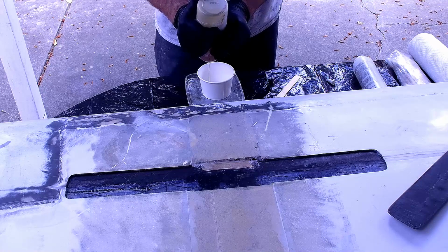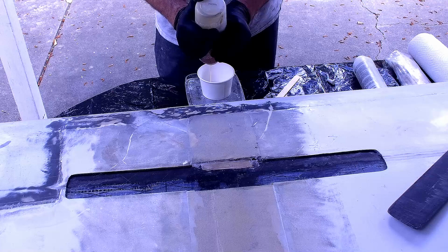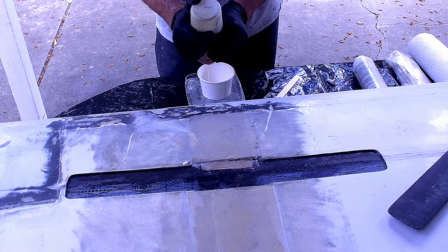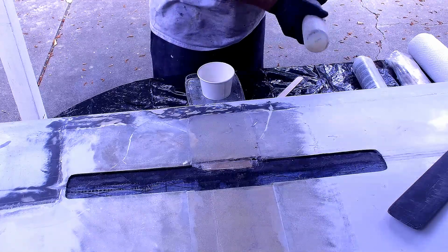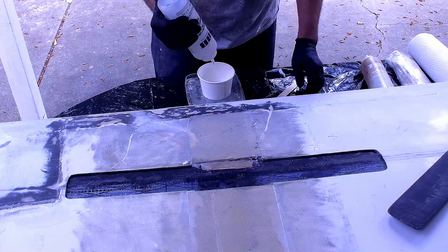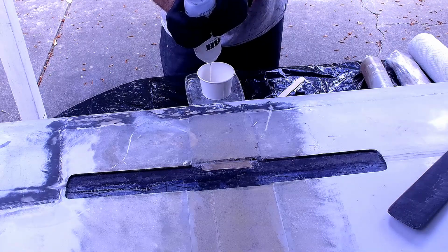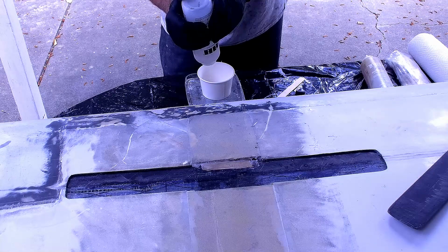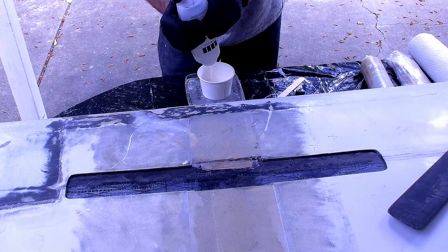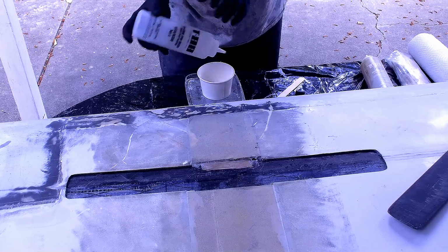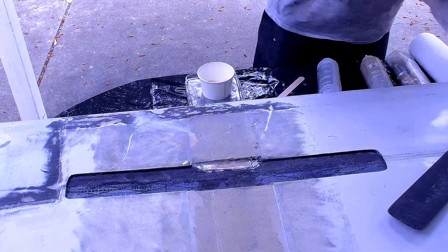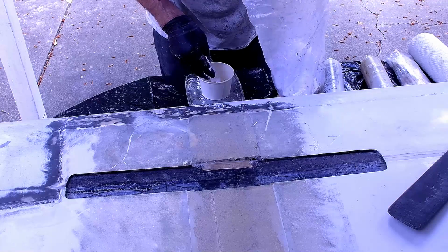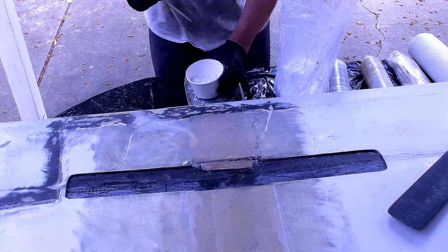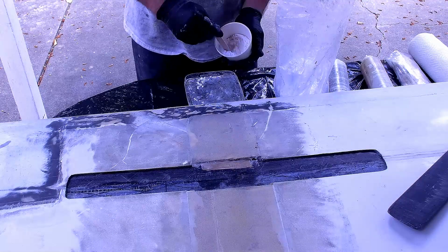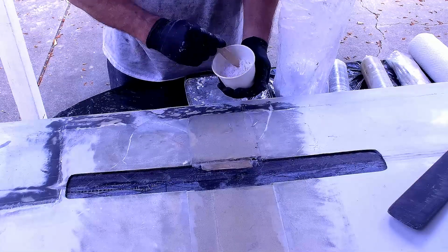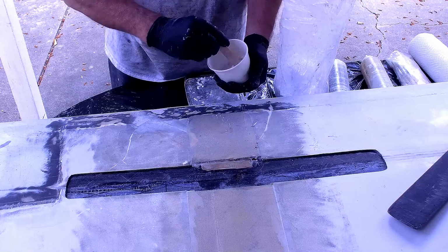So the original spar is essentially still there. A small amount was taken away with the router, and the repair is essentially a doubler that is going to be bonded to the original spar, but it's going to be flush with the wing skin, and then there's going to be a new fiberglass skin over the outside. So the spar is still broken in the middle of this repair, but the doubler will span that difference. Now there's 1 foot of doubler on each side of the spar. So the doublers are 1/8 of an inch thick, they're 1/2 inch wide. So actually I think I had 4 of them. So the full width of this is 2 inches, and 2 by 12,